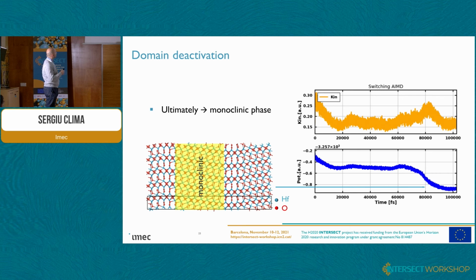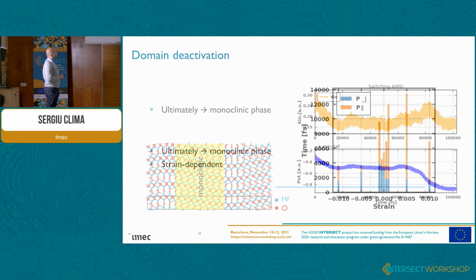So here we have a grain boundary, another grain boundary, and we have 2 grains of monoclinic, which is not ferroelectric anymore. This is a very realistic mechanism that will happen after many billions of cycles, and we'll lose the orthorhombic phase, getting more and more monoclinic phase in case we have some monoclinic nucleus to grow, for example, or the ferroelectric material is not clamped enough to hold the orthorhombic phase and falls into a much lower energy monoclinic phase.